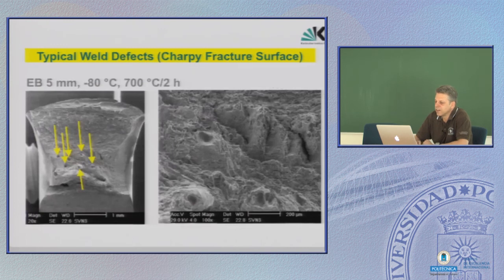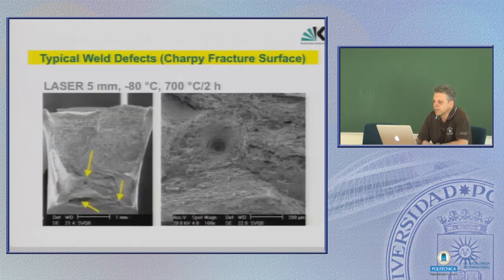And you can see that even the EB welded parts have obviously some bubbles in the material. But again, even if there are such tiny bubbles or voids, tested at minus 80 C, this never was the cause for brittle crack propagation. So you have to live with it, and you can live with it if there are not too much. The same enlarged here.